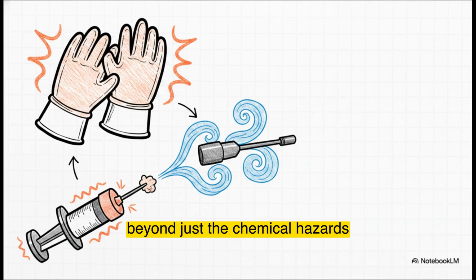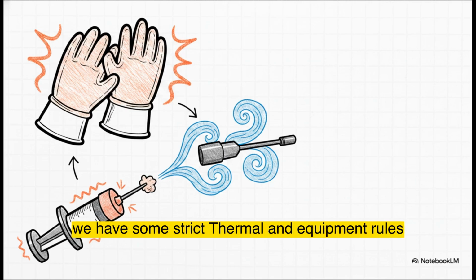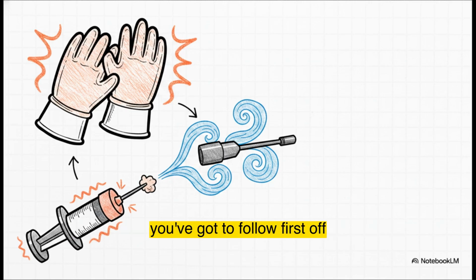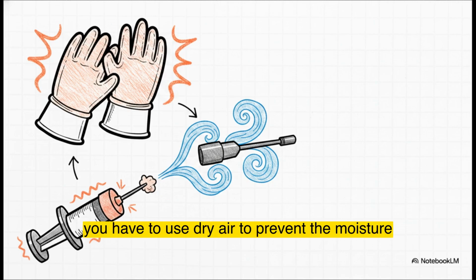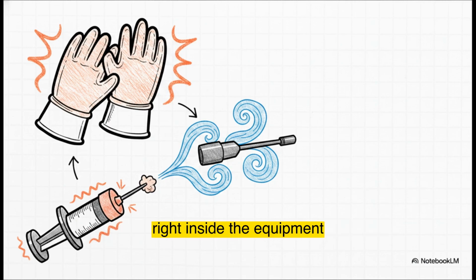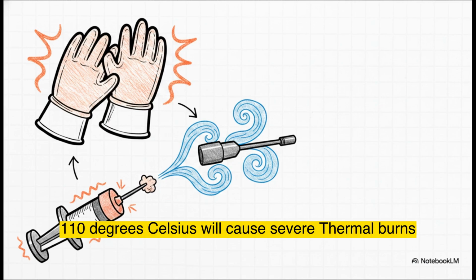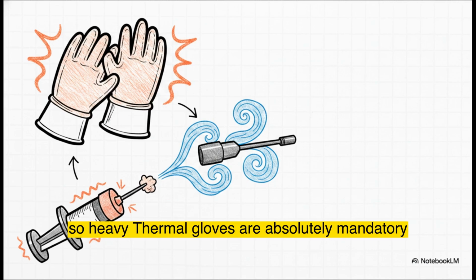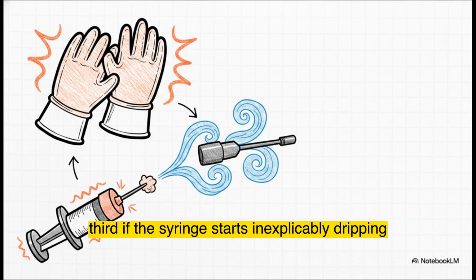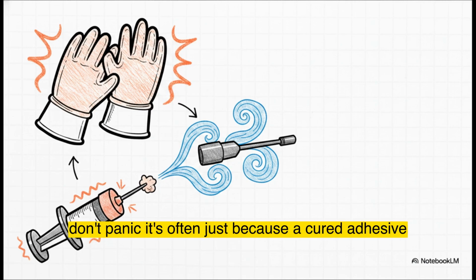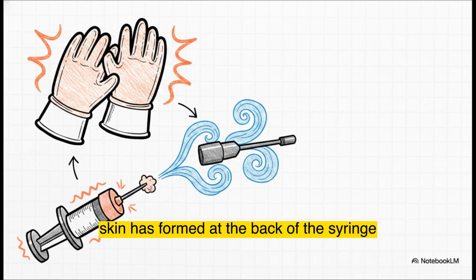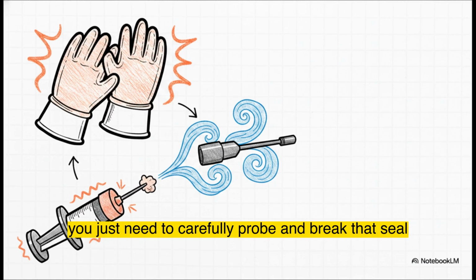Beyond just the chemical hazards, we have some strict thermal and equipment rules you've got to follow. First off, if you use pneumatic dispensing, you have to use dry air to prevent the moisture-curing adhesive from prematurely hardening right inside the equipment. Second, 110 degrees Celsius will cause severe thermal burns, so heavy thermal gloves are absolutely mandatory. Third, if the syringe starts inexplicably dripping, don't panic. It's often just because a cured adhesive skin has formed at the back of the syringe. You just need to carefully probe and break that seal.